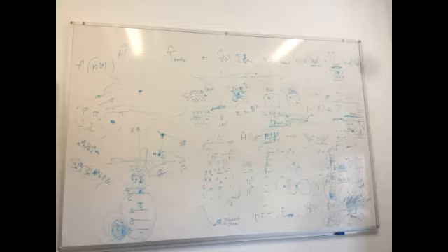You will just try to mix in various possible configurations and see, does it like to be stable? Does it like to phase separate? Does it like to go from this type of crystal structure to another crystal structure? And why is this important? Because there are crystal structures which are called layered. So let's say something like this. In this structure, lithium comes here and it can diffuse easily. So that's why layered structures are good, because they conduct lithium very easily.